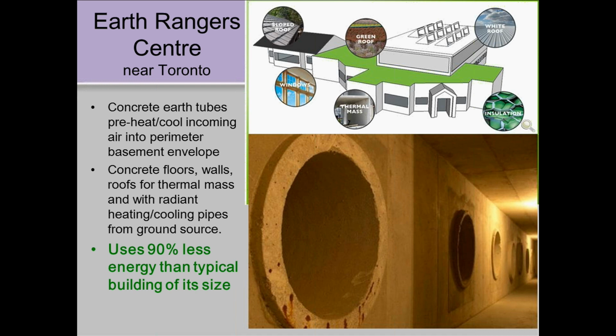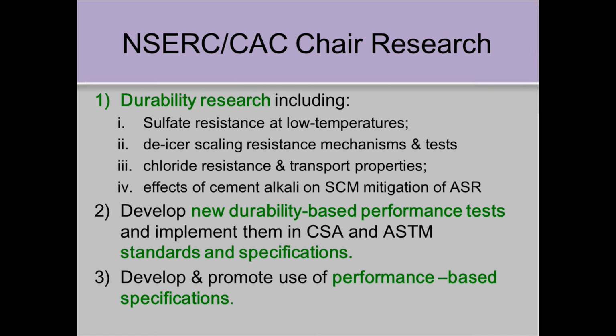It gets to about 5 or 10 degrees before it actually enters the building just by going through these earth tubes. And they have to be made of concrete because corrugated steel tubes allow water to form, and other types of tubes allow bacteria and fungi to grow, and the concrete prevents that. So concrete for these earth tubes is an important part of that design. They also use thermal mass in their design, and they've got embedded radiant cooling and heating in the ground tubes for their HVAC. And this building uses 90% less energy than an equivalent building of its size. So it's quite an impressive structure, and they're monitoring all this and updating their technologies all the time. And it was LEED Gold, and they're now going for LEED Platinum on the operation of the building.